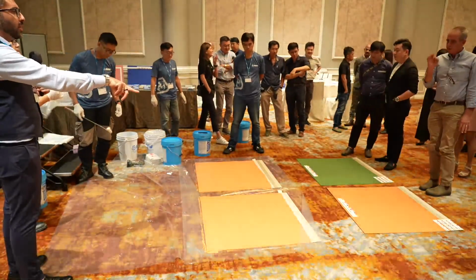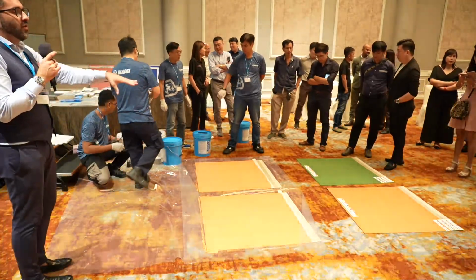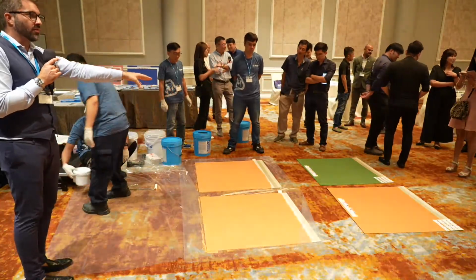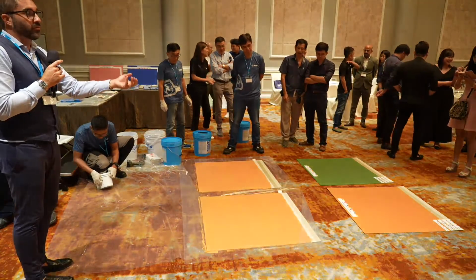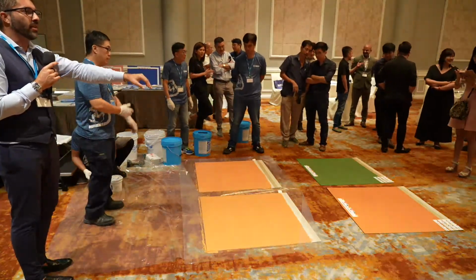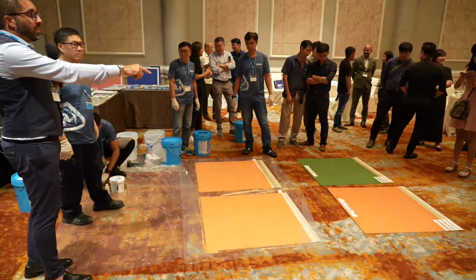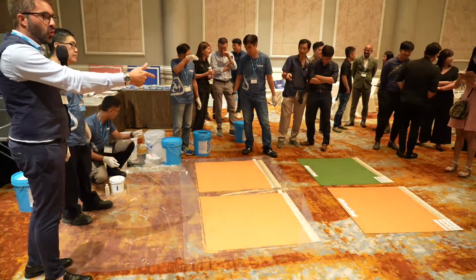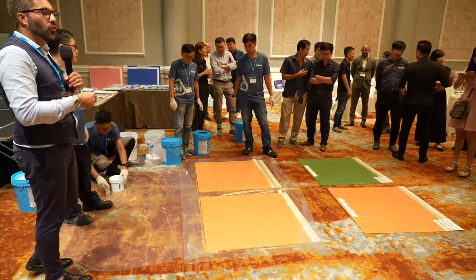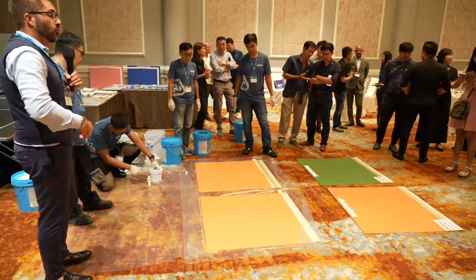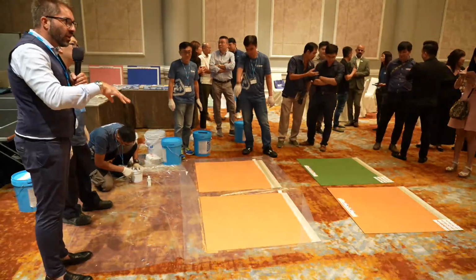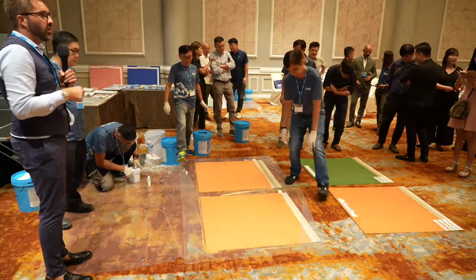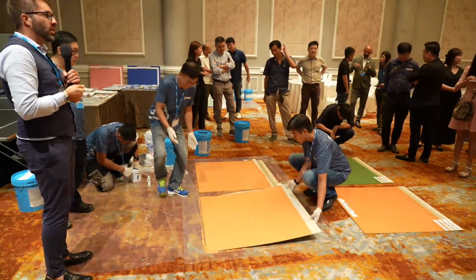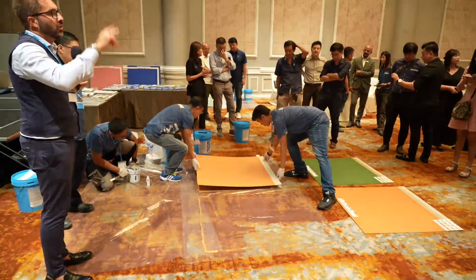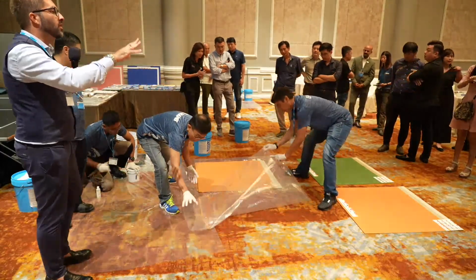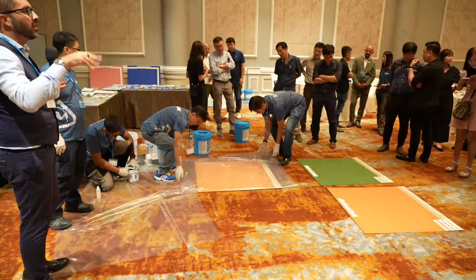Yeah, because the filler size is bigger. Bigger, why? Because we developed this product for the traffic area on asphalt. So it could also fill the asphalt directly with one layer. If we want to build this case, we can add also some sand during the application. If I need to fill a better asphalt base, for example, or to use it to level some materials. And with this one, because it's not the standard way, the epoxy part is faster. But not consider that till 5 millimeters, over 5 millimeters, it becomes...